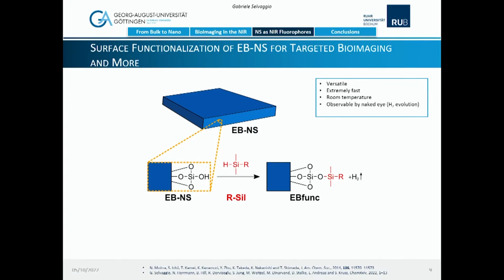And it leads to hydrogen evolution, so you can see the bubbling while the reaction runs to check if it's really happening or not. Furthermore, it is compatible to several analytical tools. Therefore, you can get seriously many confirmations from different angles that your chemistry is applicable on Egyptian blue nanosheets. And what we did was therefore to work with two hydrosilanes with two different R groups.